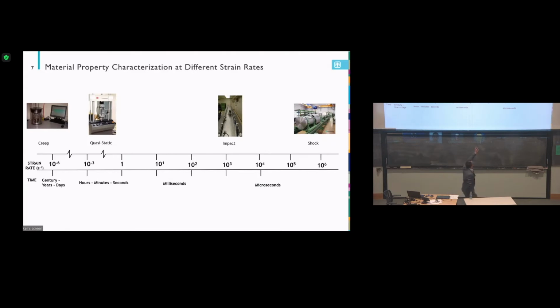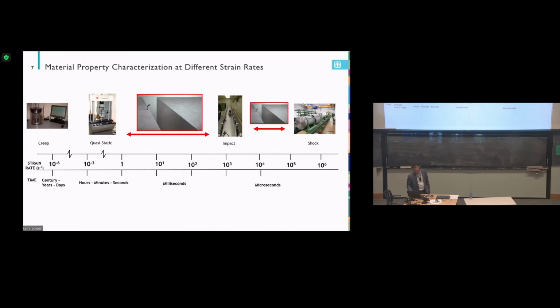Between the impact and the shock: impact still falls into the solid mechanics regime. But if you go to the shock, you get into shock physics. So it's not a pure mechanics problem, it's physics. You can see there are two gaps. Here's one big gap between the quasi-static and the impact. There's another gap between the impact and shock. Experimentally, we cannot do that at this point.